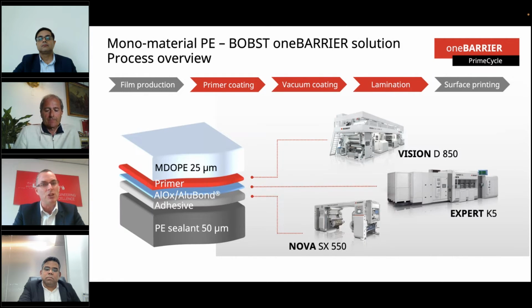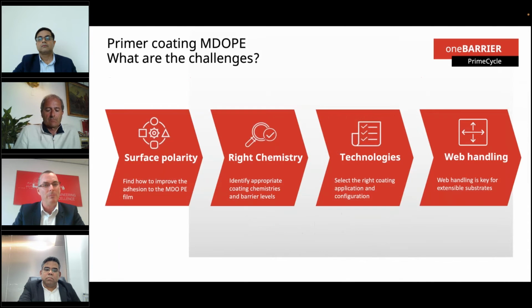So let's have a look now at the challenges we faced when developing the one barrier solution through the different process steps. Next slide, Ben. We start first with a primer coating that we apply onto the MDO-PE based film. Firstly, we have a challenge with surface polarity based upon the non-polar nature of the MDO-PE. We need to make sure the primer adheres very well to the film surface, which was achieved via optimized treatment on the coating line, prior to applying the primer coating.